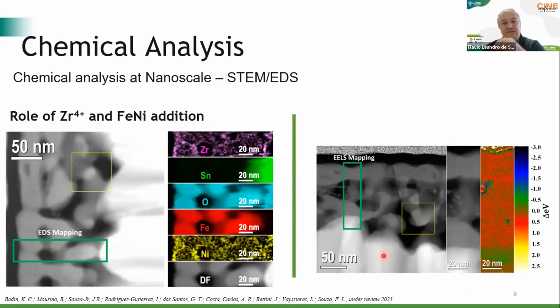And then just to make sure that we are being clear, we took advantage of the sample preparation, and we performed scanning transmission electron microscopy together with EDS to give you a chemical map. Here we have 3 important pieces of information. The first one, we see only the tin, which is the FTO, the fluorine doped tin oxide.